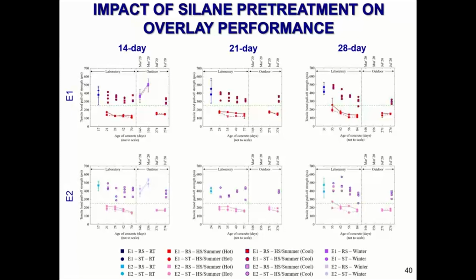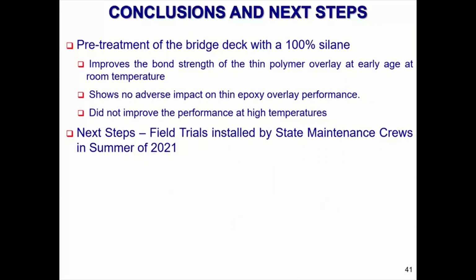But basically what you're seeing is at early age, it does improve the bond strength. And the older the concrete gets, the less of an impact it has using a silane pretreatment. But at the same time, it doesn't show any negative impact to applying the silane before the thin polymer overlays. It probably needs a little more research to check a couple more silanes and a couple more epoxy materials to check for material compatibility.